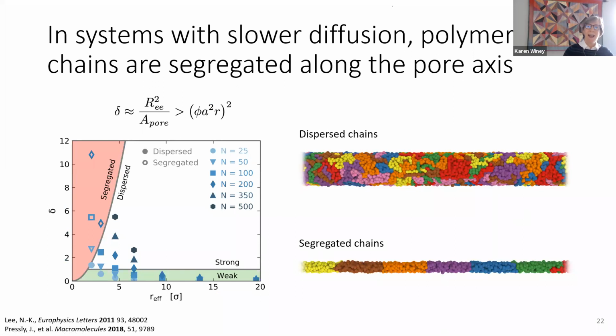until we appreciated what was happening in terms of morphology. When the pore got very, very small, the chains segregated. Now you can imagine that for this orange chain and this purple chain to exchange, they have to become very elongated and wiggle past one another. It's a huge entropic barrier for diffusion once you get this small in radius and you have this segregation of chains. What's plotted here on the right is this confinement parameter as a function of pore radius. The lines on here are from work by Lee, describing the difference between weak and strong, but these are both still dispersed.